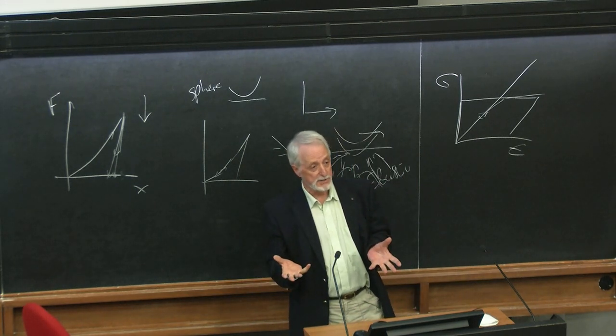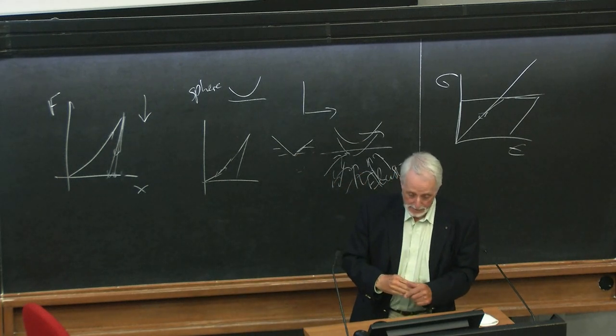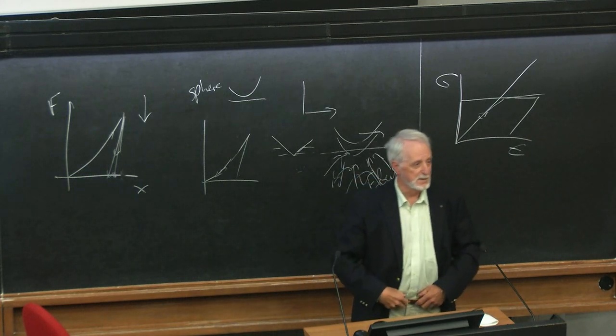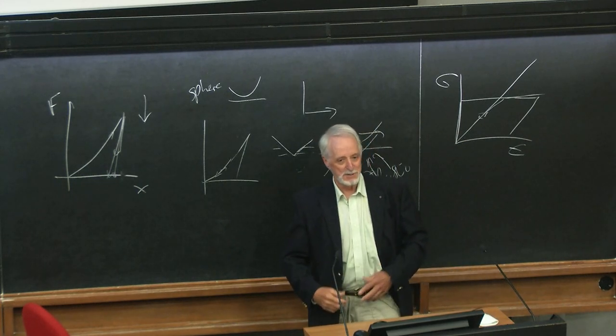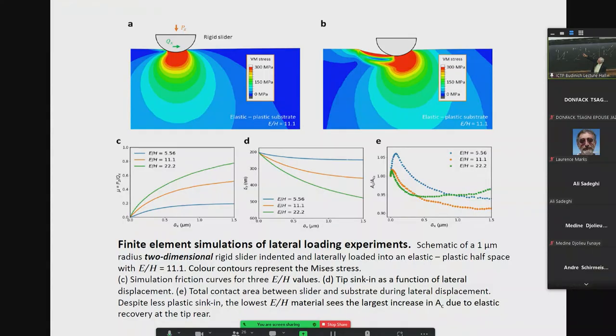And we know that the yield strain has some effect there, but it's actually quite difficult to model that. We did do one finite element simulation for this, which broadly shows the behavior you've seen there. As you change the E over H ratio, you can change these curves. You get behavior which shows that initial rise there.